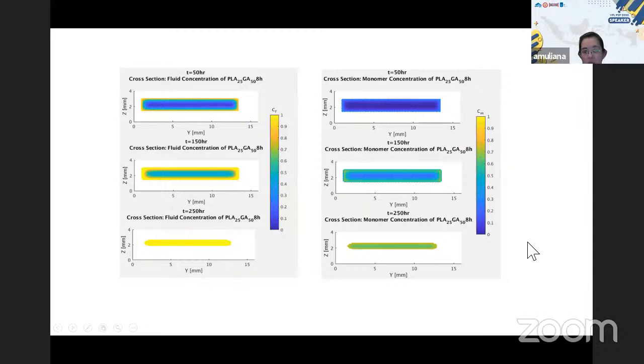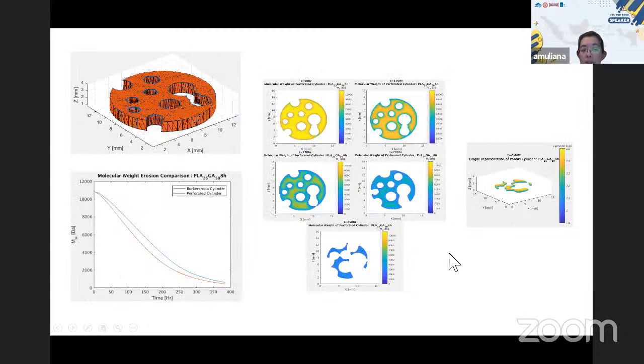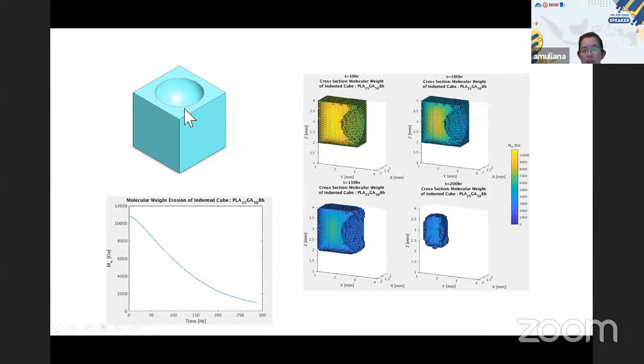So now we also want to see what if we have a perforated polymer, because when we use it in a scaffold, it's often a porous domain, right? It's not going to be a solid disc. As expected, when you have perforations, it degrades faster. But one thing, when you do have perforations, you might end up at the later stage with this component breaking into pieces, because I guess the junction here would degrade away as the erosion takes place. And here just to show you what if we have another shape, right? Because all this geometry, the initial geometry, would affect the degradation process.